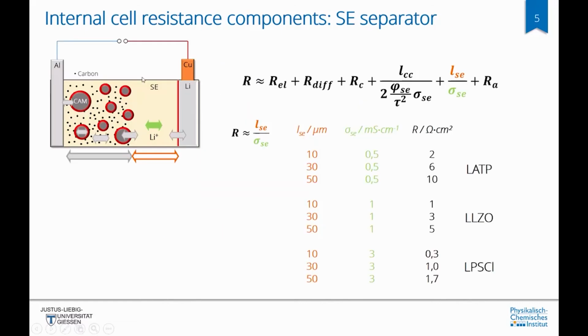First, we have a look at the separator layer between cathode and anode. And this focuses on lithium-ion conduction and the thickness. So the internal resistance value in ohm square centimeters can be calculated by the thickness of the solid electrolyte divided by its ionic conductivity. And if we compare several electrolytes, for example, LATP, LLZO, and the argyrodite, then we can see that the ohm square centimeter values are relatively low, all below 10 ohm square centimeters, which means that technically all of these can in principle be used for the solid electrolyte.